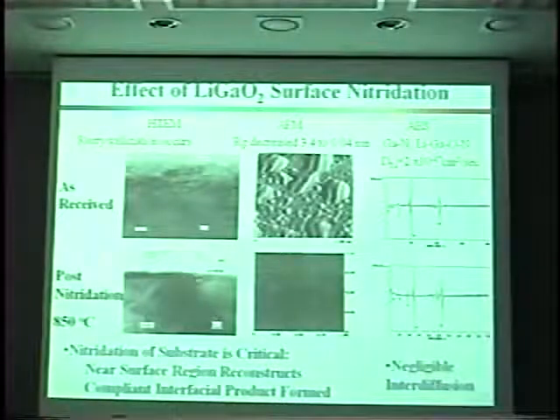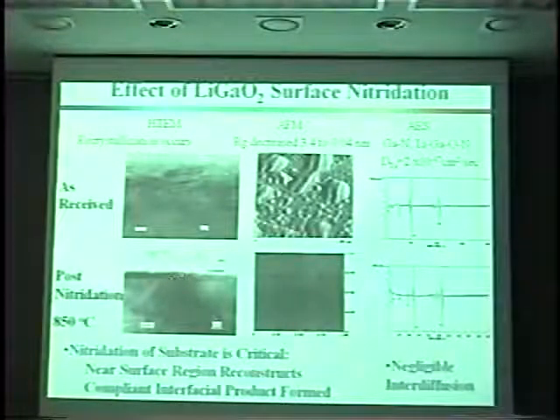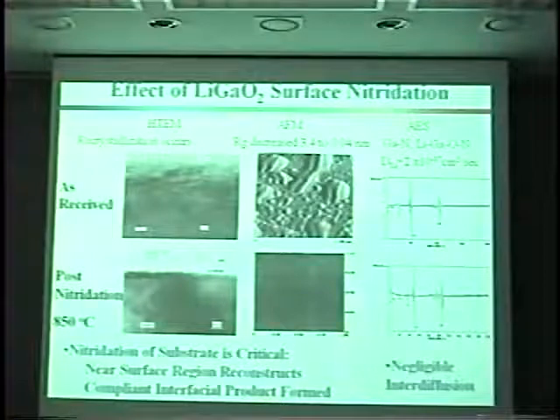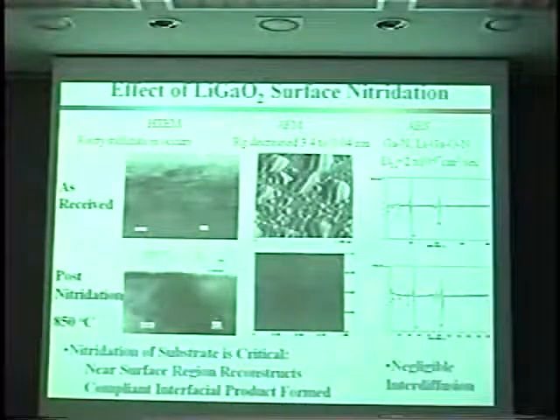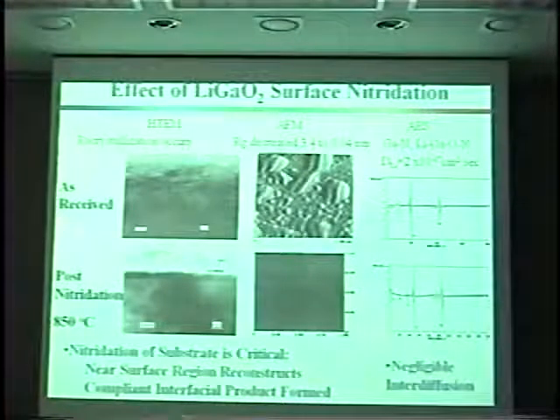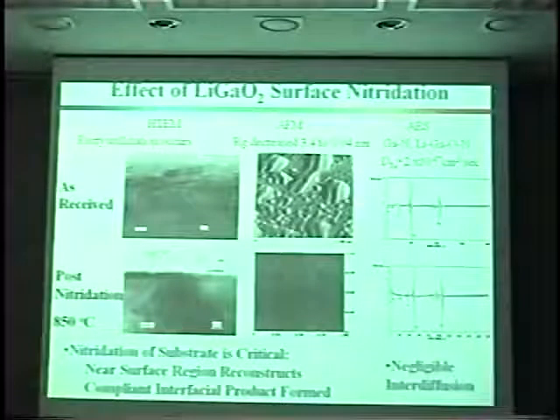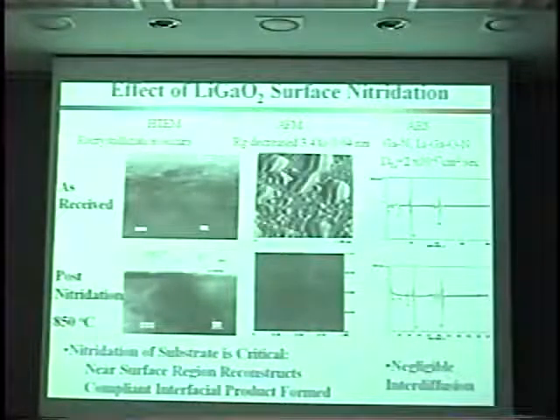We were also worried about lithium diffusion into the gallium nitride. This layer served as a nice barrier. We saw no evidence of diffusion. In fact, we estimated the lithium diffusivity at about 10 to the minus 17. Here are some profiles that we took. But the key to this technology, and this is a recurring theme, is to be able to do interfacial engineering: to design that interface to be compliant, to serve as a barrier layer, and, as I'm going to show you, to self-release with a small amount of strain that's put in as a result of cooling. And doing that correctly by design, perhaps as you saw, just using thermodynamics to choose an appropriate temperature.